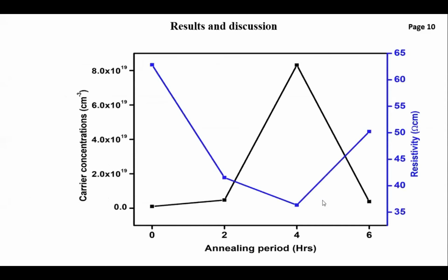Also, the electrical properties were conducted to determine the carrier concentration as well as the resistivity of the film. As we can see from the diagram, at 0 hours the concentration is low, which then increases with increasing annealing period. We have the highest concentration at 4 hours. And for the resistivity, we have the lowest resistivity at 4 hours. Therefore, 4 hours is taken to be the best for the electrical properties.